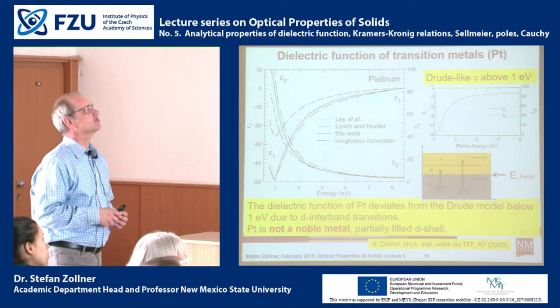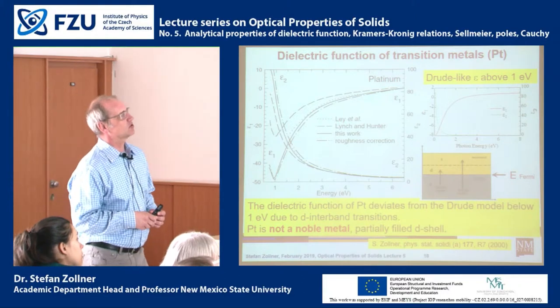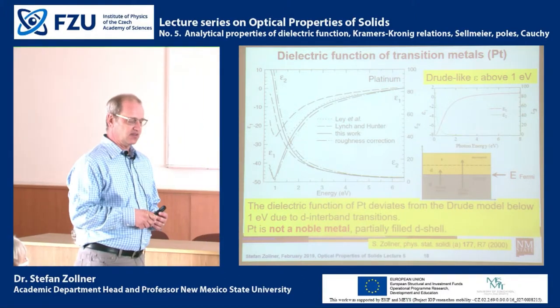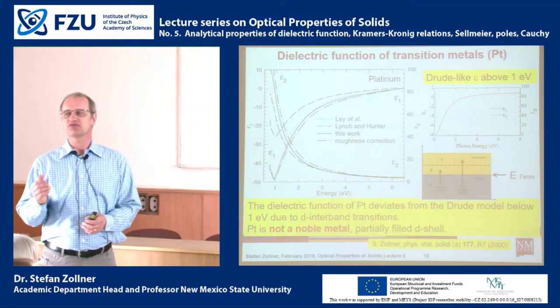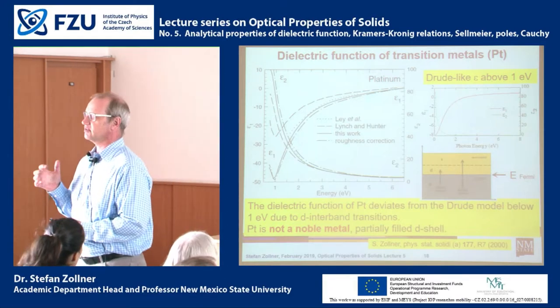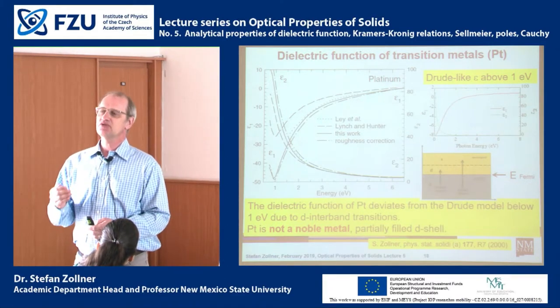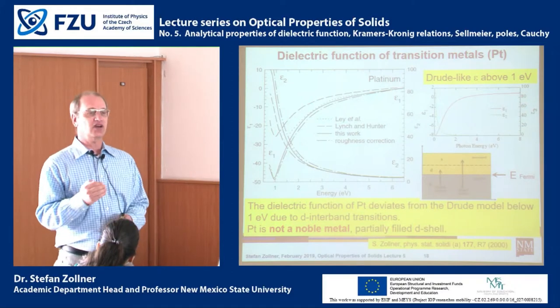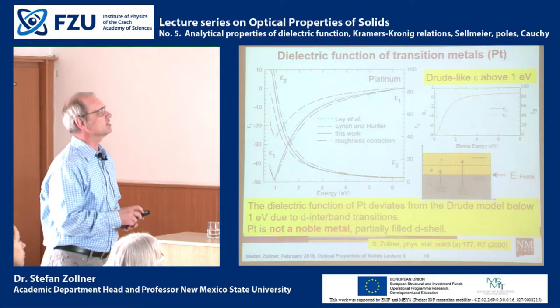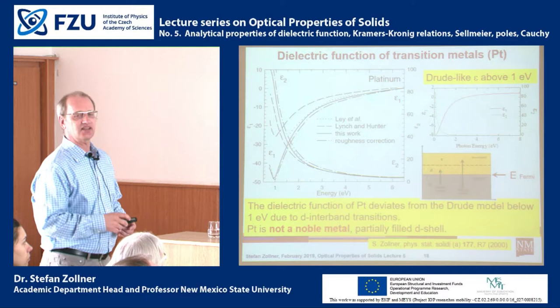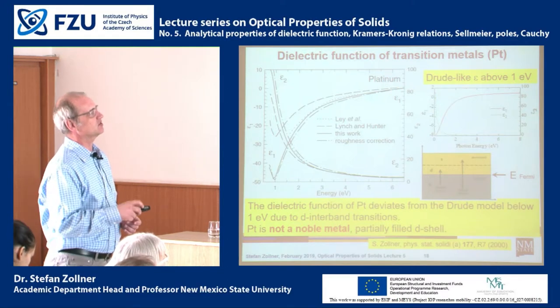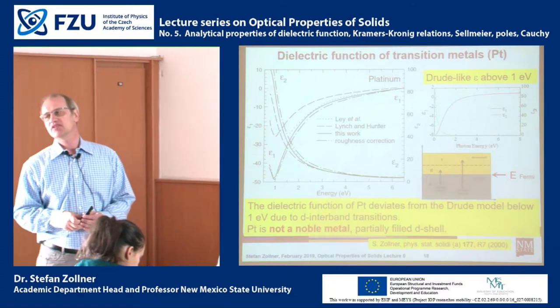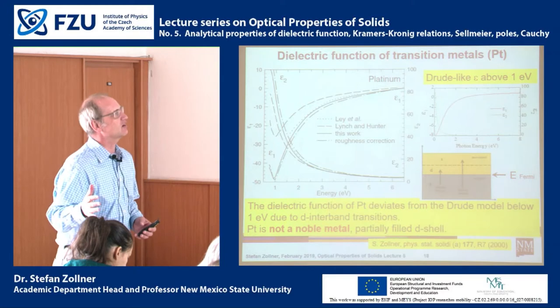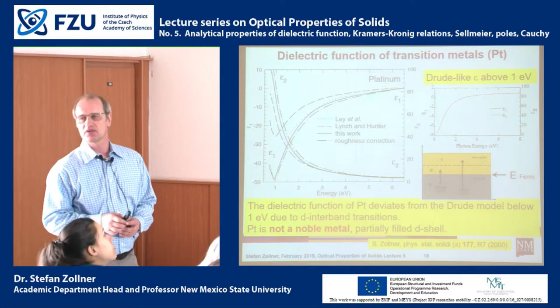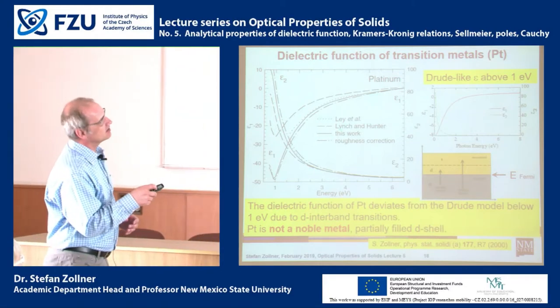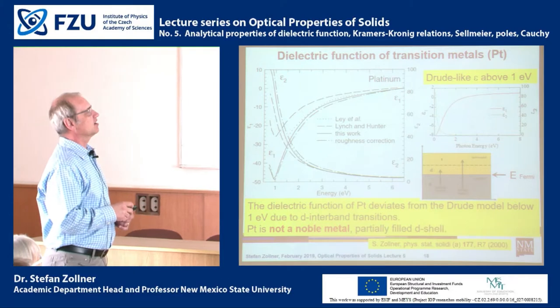article by Lynch and Hunter in Palik's handbook on optical constants, David Lynch writes that transition metals never really exhibit Drude absorption. Transition metals never really exhibit Drude behavior in the infrared. And the reason why transition metals are not Drude metals in the infrared is because of these D states and these interband transitions. They can happen at arbitrarily low energies, and therefore, even going to longer and longer wavelengths, platinum will never be a Drude metal. And we also see that in nickel. So that is the opinion that was expressed by David Lynch.